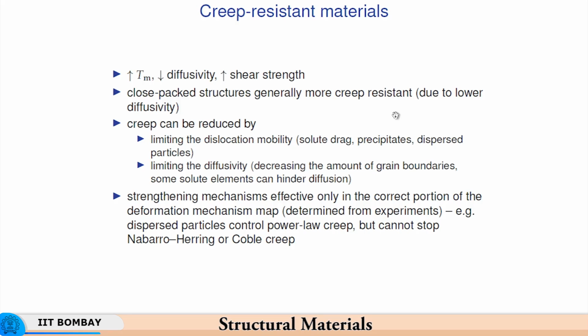But on the other hand, body centered cubic materials which are refractory alloys, molybdenum, tantalum, may not be tantalum, I am not sure about tantalum, but molybdenum, tungsten. So, these are all materials which are creep resistant because of their body centered cubic structure. So, diffusivity is curtailed, and then you